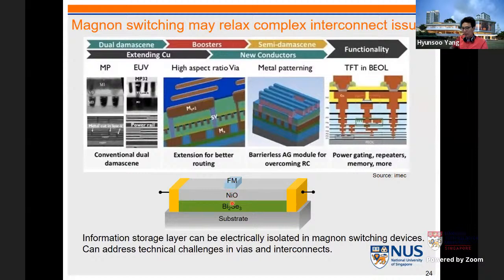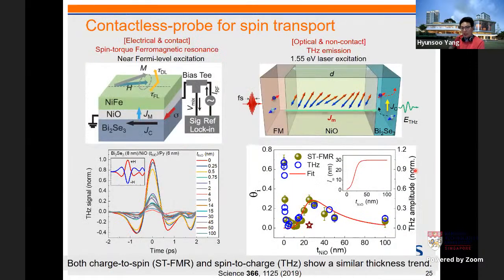Basically, we do not need to make holes and then vias and then fill with this copper material. So probably we can relax the requirement of this interconnect and via requirement. So we put nickel oxide because this is a very well-known insulating antiferromagnet. It is also very easy to deposit using conventional sputtering. We use bismuth selenide to generate strong spin current.